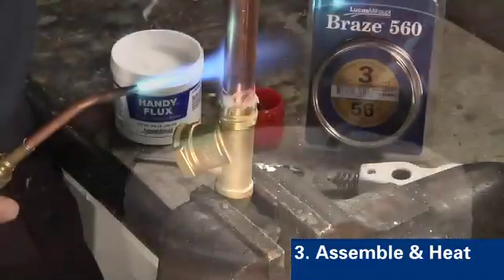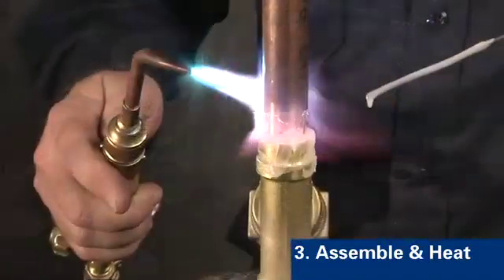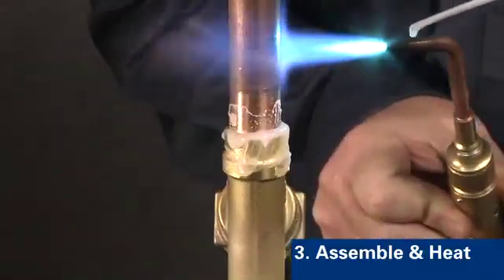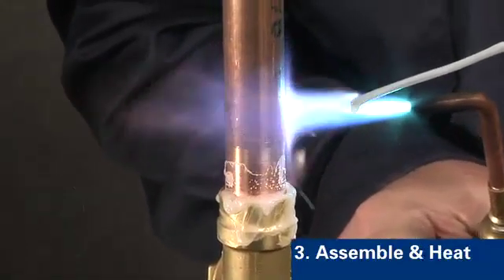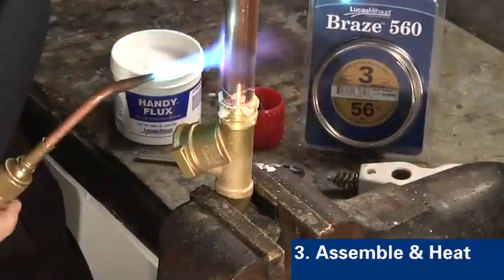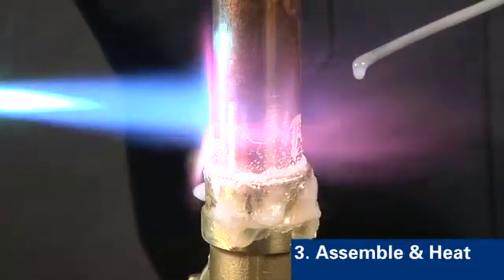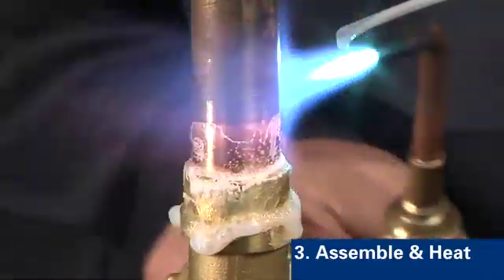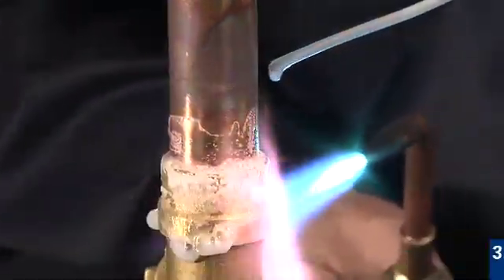Step 3 is to assemble the joint and begin heating. Apply heat with a reducing flame to minimize oxidation of the part. Heat the part evenly and uniformly. The flux will indicate when to apply filler material to the braze joint.